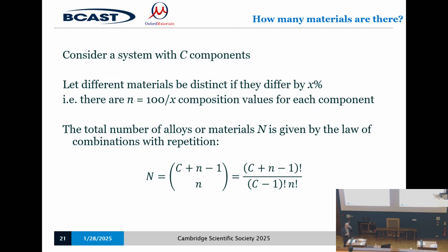Specification is normally used commercially so that you can sue someone if the material fails. When someone supplies you with a material, they supply within a specification, within a range of composition. It's to do with how good we are at making the material and at having reasonably consistent properties. Typically for engineering, that's called the specification. If the specification is X%, if we change the material's content by X% of one of the components, then there are N = 100/X different composition values. That's the number of points along one of those axes in those triangles and tetrahedra I was showing you.